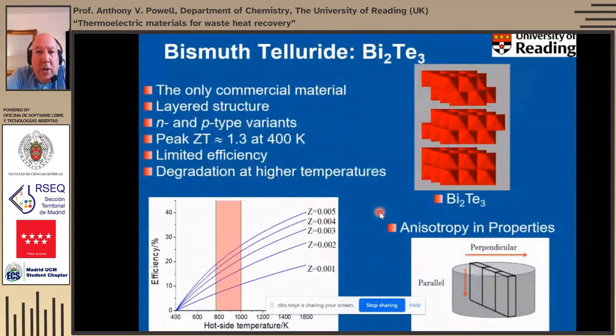The only current commercial material is this one, which is bismuth telluride. This is a layered structure, so it's these blocks of octahedra, like the metal dichalcogenide structure, but taking pairs of them which share common faces. So we have these paired blocks and then a van der Waals gap and then another block of bismuth telluride. So it's a layered structure.